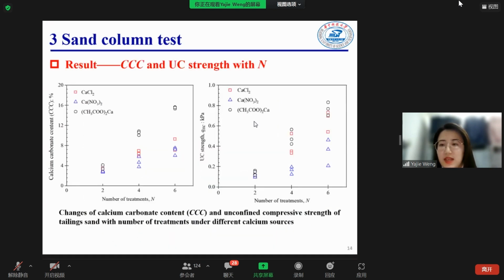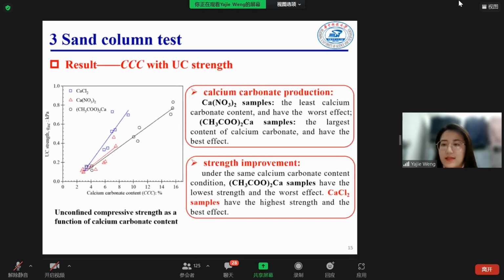The results show that calcium carbonate content and unconfined compressive strength both increase with the number of treatments under different calcium sources. From this picture, we can see that in terms of calcium carbonate production, the tailings column with calcium nitrate produces the least calcium carbonate content, and the calcium acetate sample has the highest calcium carbonate content. As for strength improvement ability under the same calcium carbonate content condition, the calcium acetate sample has the lowest strength. Calcium chloride has the highest strength and the best cementing effect.